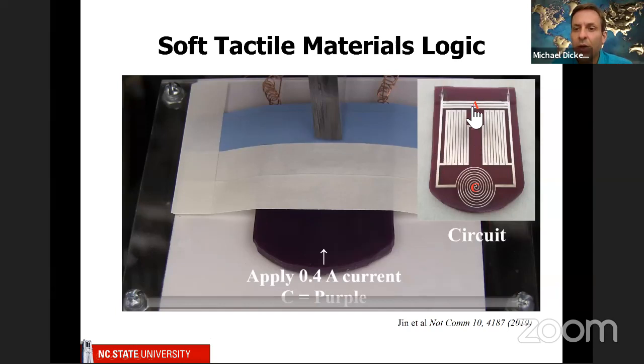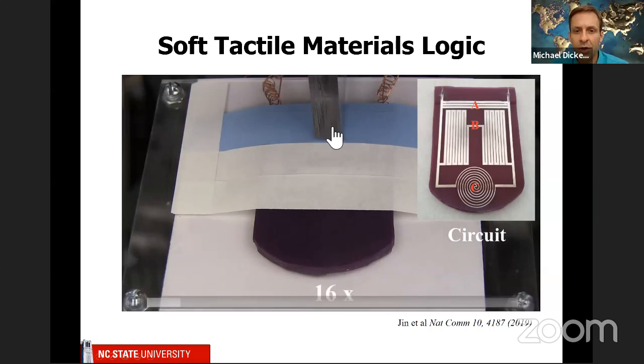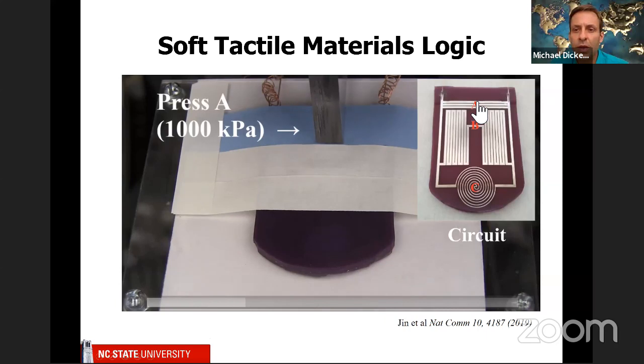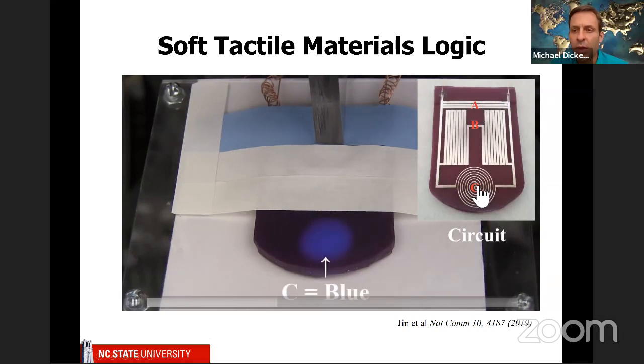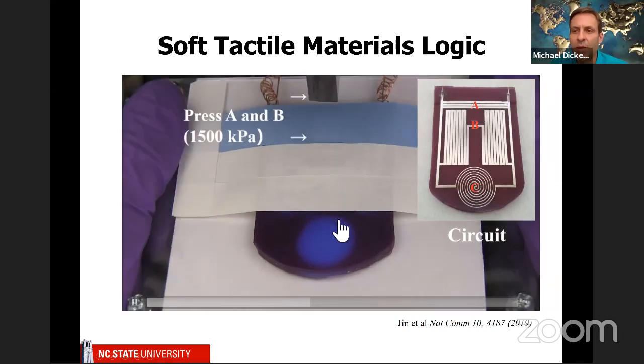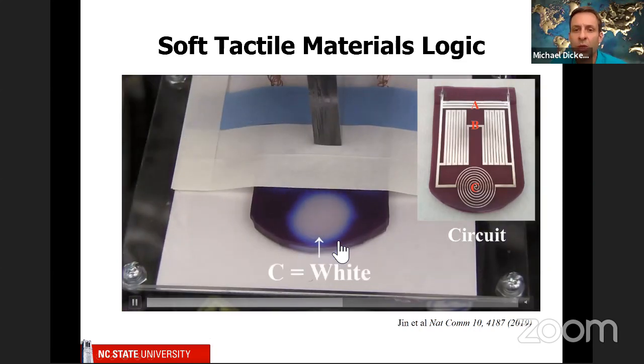All right, so now that I've said all that, again, this is very, very modest, but here's how we did it. We have a very simple circuit of liquid metal. There's A, B, and C, and current roughly goes through these 1/3, 1/3, 1/3, if you'll think of it that way. We flip it over, and this is region C, so it looks purple. We're running current through it, but not enough to see a color change. We then start the experiment where we start pushing in region A. When you do that, you squish the liquid metal here, redirecting current to region C, evoking a response in a kind of distal place, in a different place than when you're pushing.